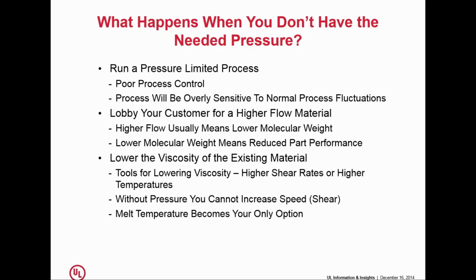Well, without enough pressure, you're stuck with running a pressure-limited process, which means you don't have velocity control, which means you have poor process control. Your process will become overly sensitive to normal process fluctuations. I always know when someone's having difficulty running with enough pressure because they'll call me up and say, well, you know, the batch we ran before had a flow rate of 8 grams per 10 minutes, and it processed fine, and now we're running a 7 and we're having difficulty. If that's happening to you, you either have the machine set up to be artificially capped at too low of a pressure, or you have a machine that is pressure limited.